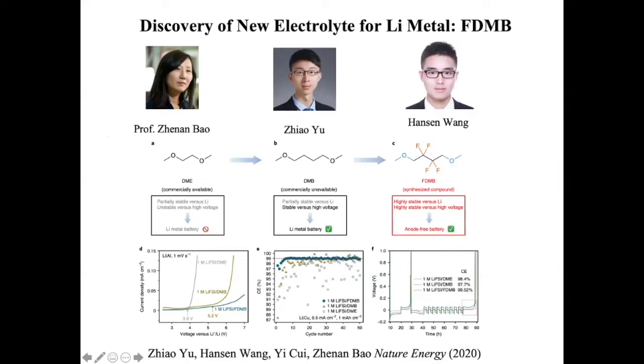And recently, we discovered a new molecule functioning as a solvent, highlighted right here, called FDMB. This is a solvent based on rational design. We know DME can form a good SEI, right? This is an ether, but DME is not stable against high voltage. Below 4 volt versus lithium, it starts to decompose quite a bit. So we want to extend this chain further, now becoming more of a hydrocarbon chain. This increases the stability and still maintains the ether, the two oxygens, to form a good SEI. However, this is not stable enough, the DMB. We need to add in fluorine, two fluorines right here. It turned out this molecule didn't exist before.